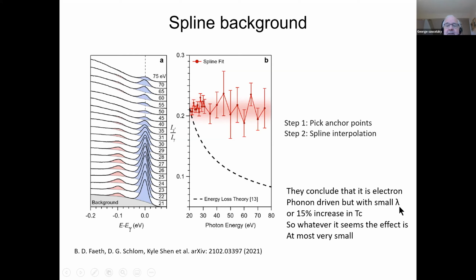And if you use that electron-phonon coupling to enhance the TC that already was there because of the electron doping, which is about 40 degrees Kelvin. So just from electron doping, the temperature goes up to 40 Kelvin. And you would get about a 15% increase, okay? So it would go to 46 or something like that, which means that it's very small.